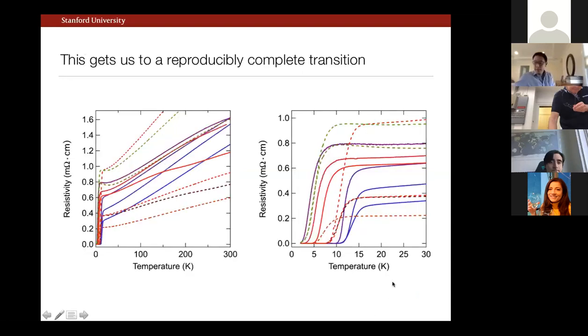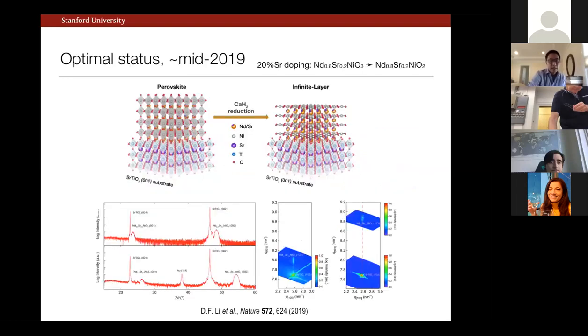So this gets us to basically a reproducibly complete transition. Still at this stage, bouncing around quite a bit. So I won't go into the details, but basically now we can get real zeros of the resistance, with quite a bit of scatter for films that were nominally grown and reduced in the same conditions. We've made some progress on this, as I'll show you as we go along. And so as of kind of a year ago, this is where we stood, and Denver's first paper on this topic. So let me just walk you through briefly the status at that time. This is just a nice illustration of this calcium hydride reduction reaction.